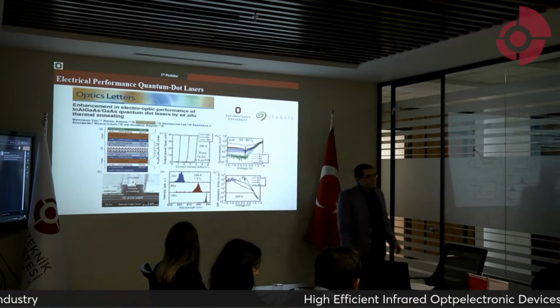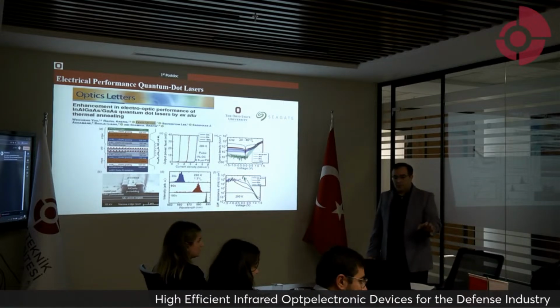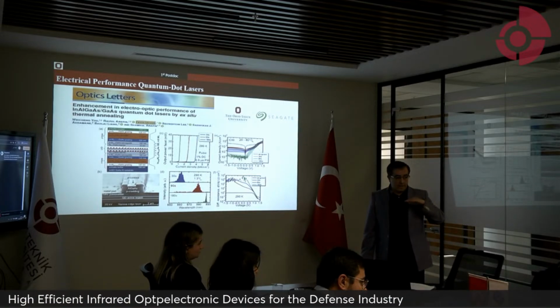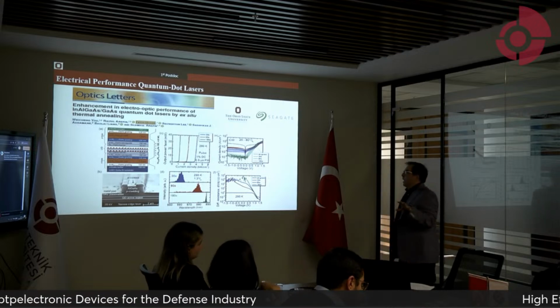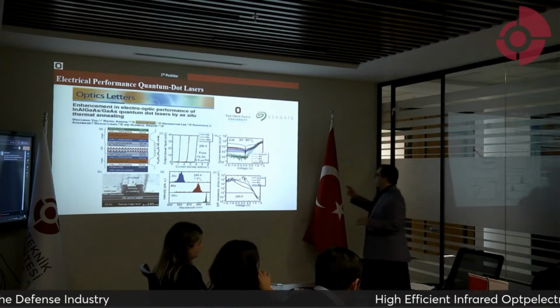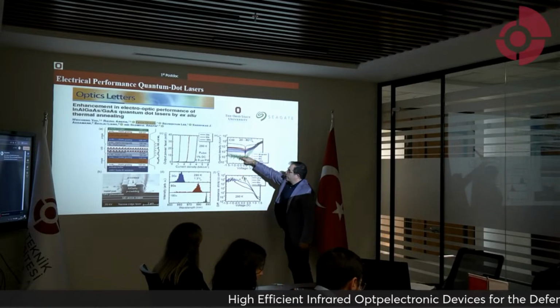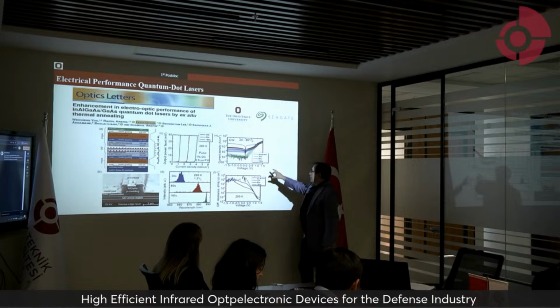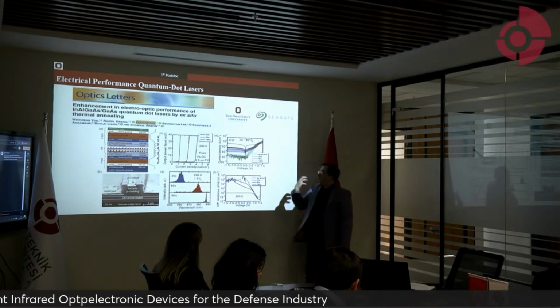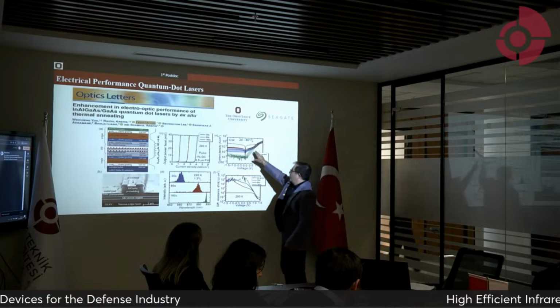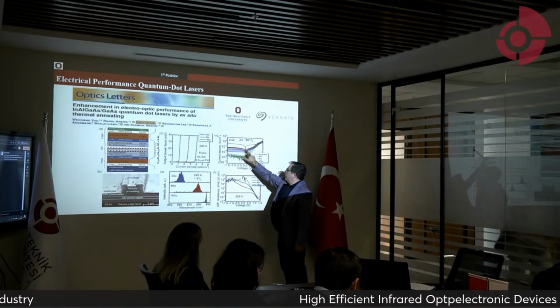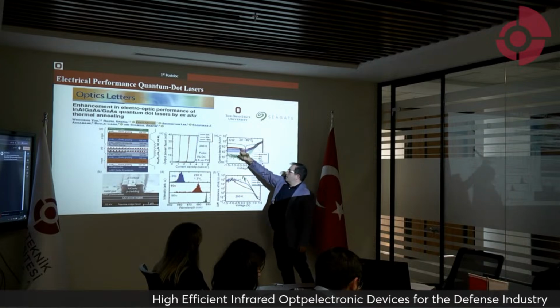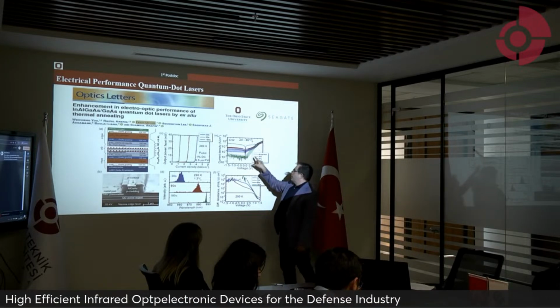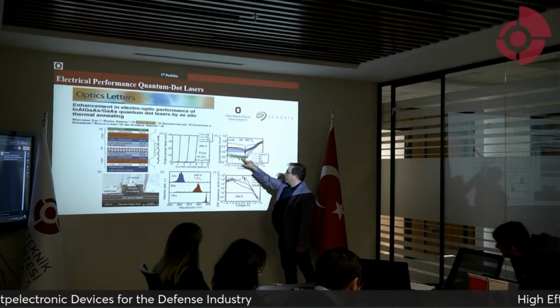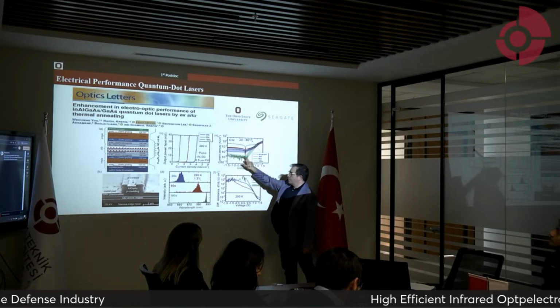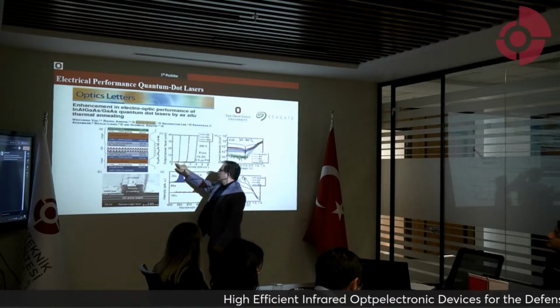I saw that after 2 years they understood that they had forgotten a process. We say annealing. When they do annealing, the device structure gets better and the result gets better. For example, this is the annealing time. When you anneal for, for example, 30 seconds, your device shows better performance, and with longer annealing time, we reach these results. And you can also see the LI graph.